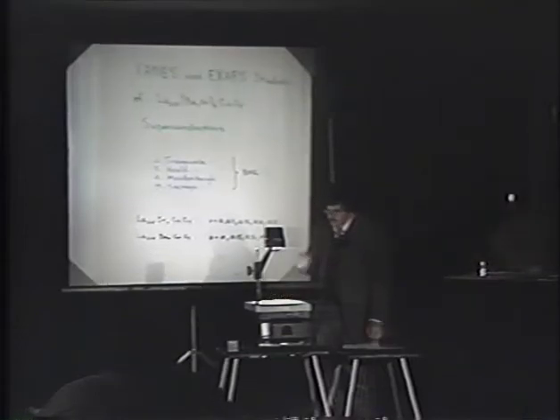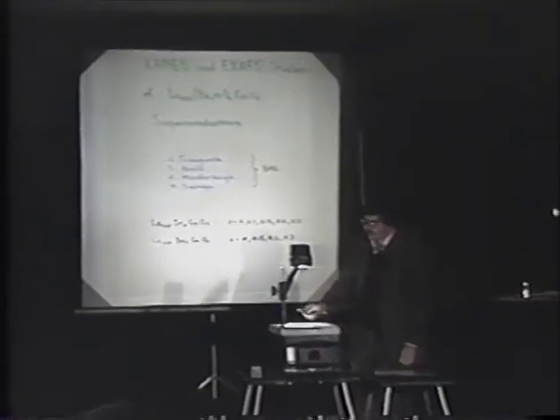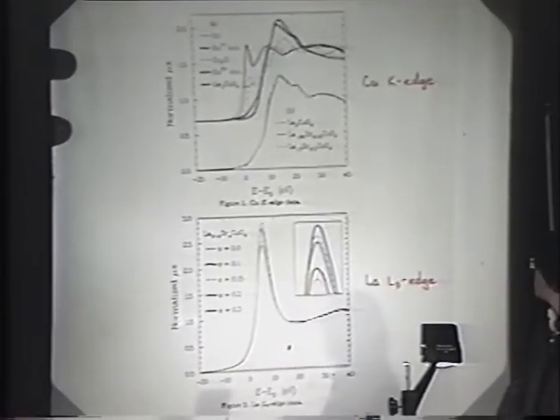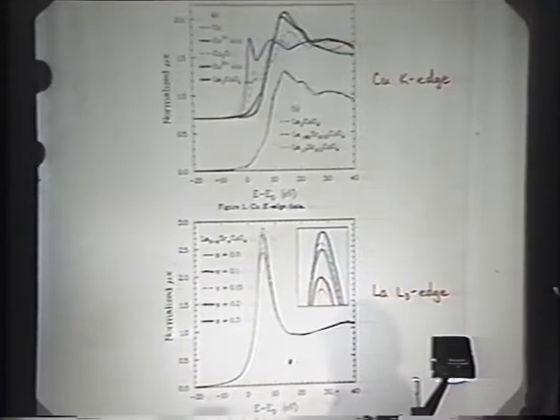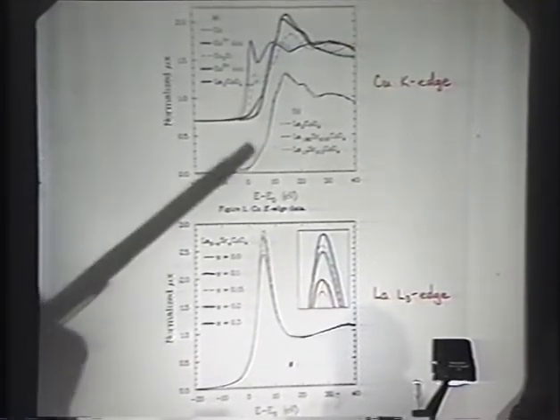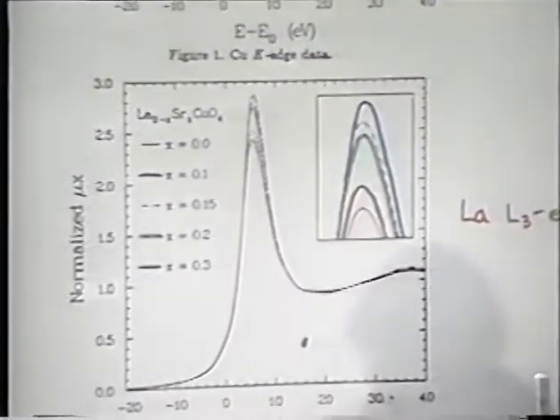Okay, I'd like to talk about some X-ray absorption measurements we've made on lanthanum, barium, and strontium copper oxide compounds. We've measured both X-ray absorption near edge structure and EXAFS. We've looked at strontium doping from 0 to 0.3 and barium doping from 0 to 0.3. Since there's not much time, this is mainly going to be an advertisement. Since there's no time to go into details, we've made accurately calibrated measurements of the copper K-edge in these materials and also in a series of reference materials. We've also looked at the lanthanum L3 and L2 edges, also the barium L3 edge.